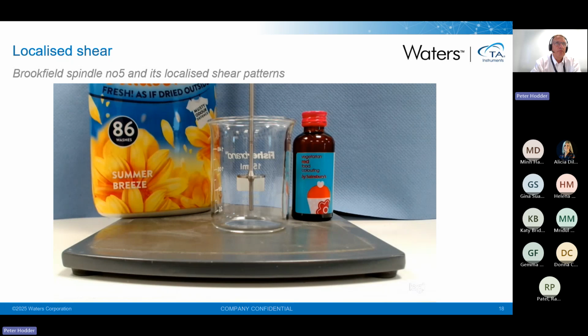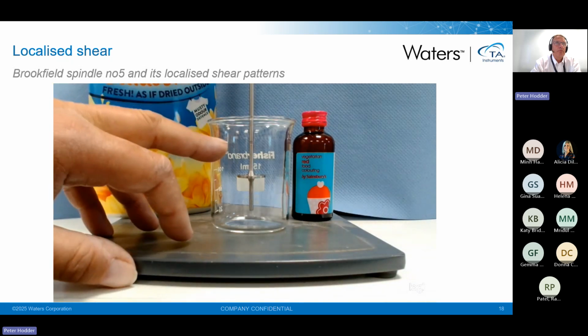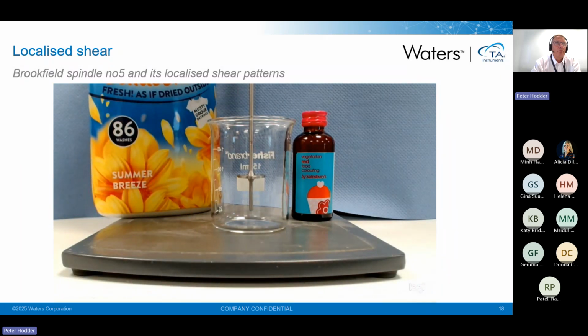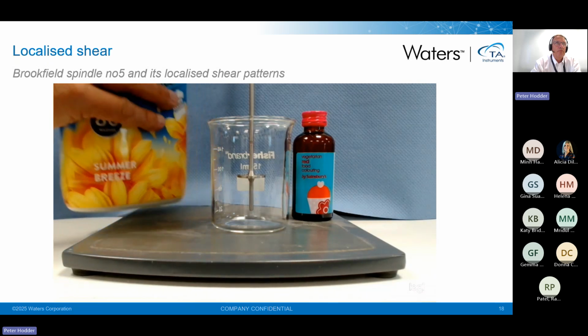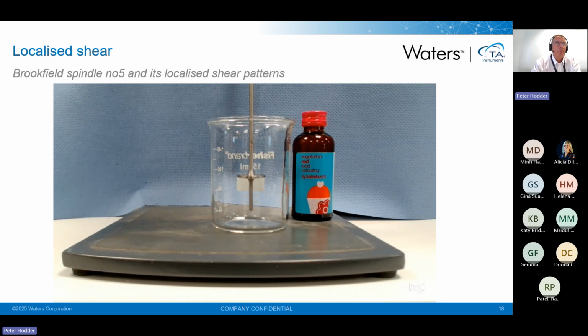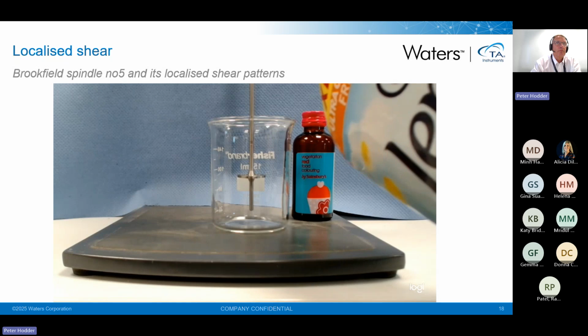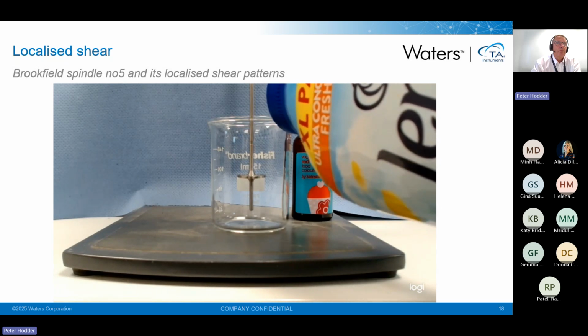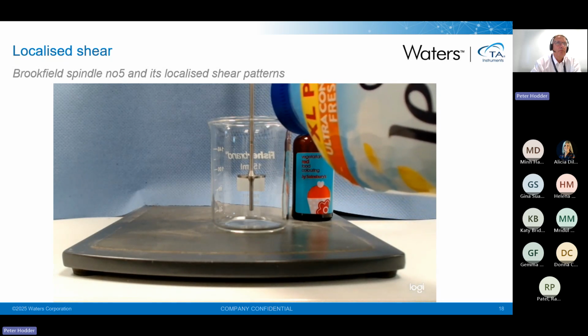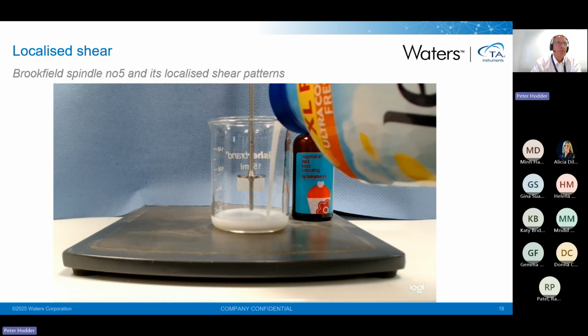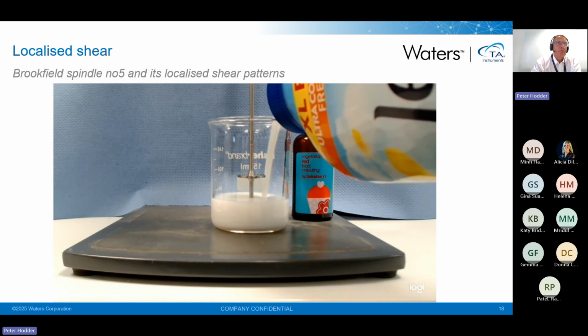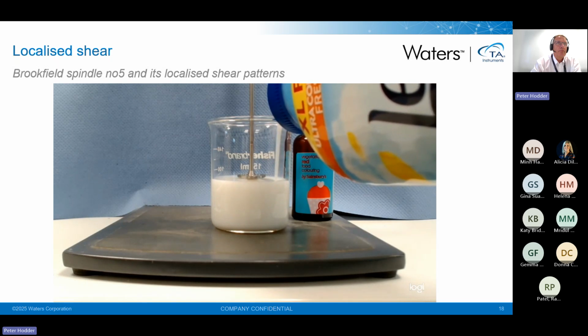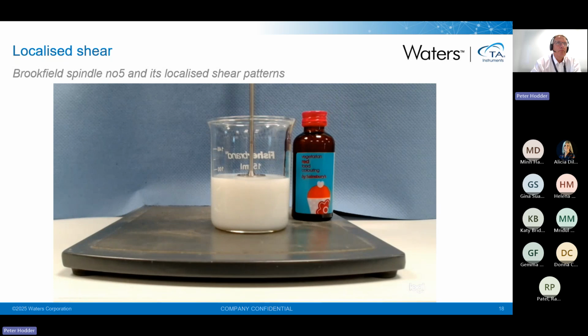So what I'm going to do is, normally you would fill up to the marker line on the system there, and you would submerge the spindle in at an angle so you wouldn't trap air bubbles, but I want to actually just fill it so that the spindle is just at the surface. Not an unusual way of being used, but a way to demonstrate, because as you can see, the Lenor fabric conditioner is coloured and opaque, so we can't see the spindle. It's submerged. I'm just going to pour enough in there just so that the spindle is at the actual surface.